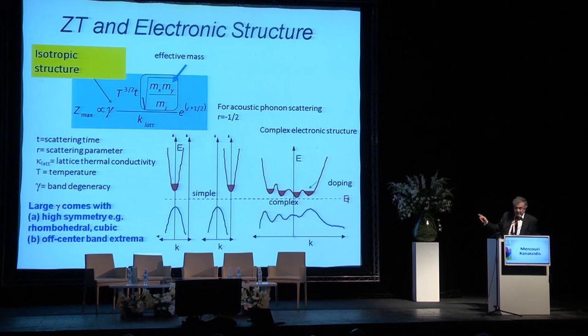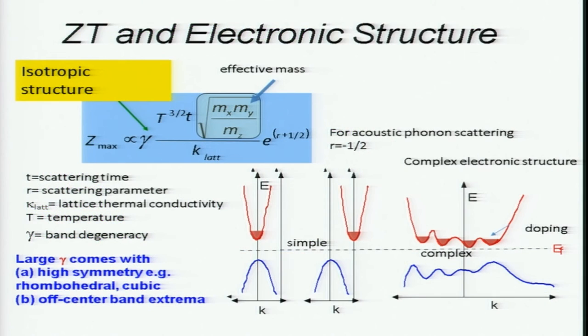Here we have three cartoons. The two left cartoons have the red electronic band, that's a single band of electrons doing the conduction. And the cartoon on the right has four bands filled with electrons, the red curves. It has up to four bands. It's a complex electronic structure. And that's the type of material that will give you higher efficiencies.